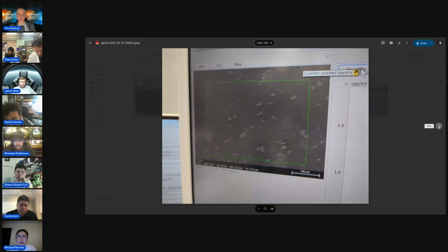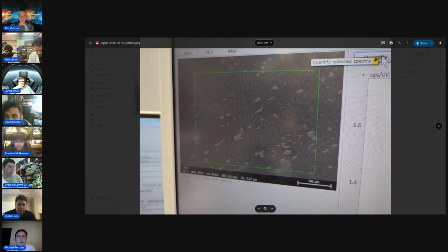These were very preliminary because we didn't have time to sputter coat before this APEC thing, but we wanted to show that we're getting the data now. So the epoxy around the samples was reflecting a lot of electrons, just charging up like crazy. So we weren't able to get a lot of the electron beam onto the sample itself. So we didn't get as many counts as we otherwise would.